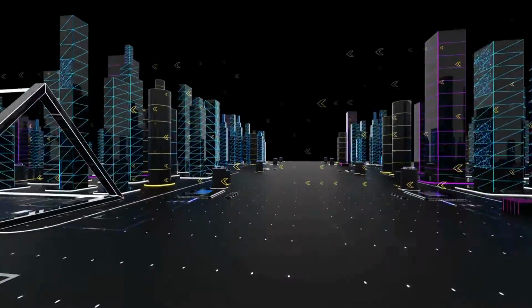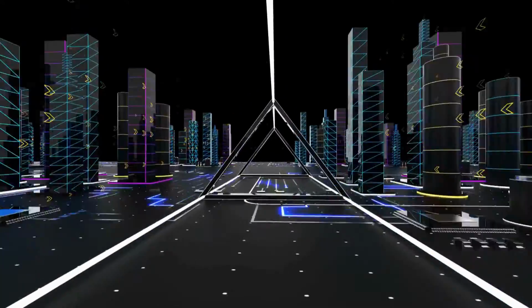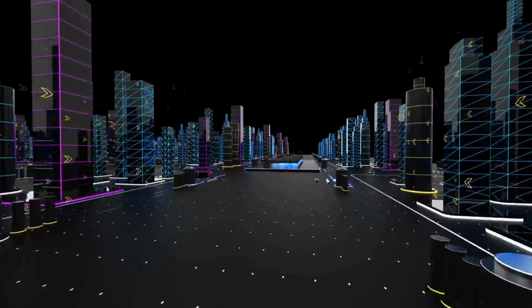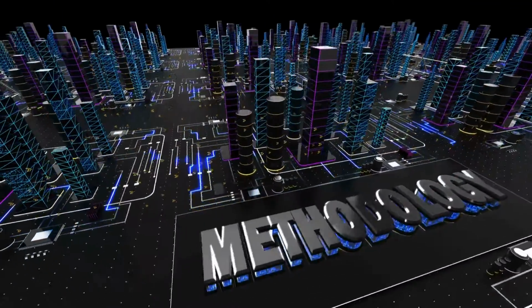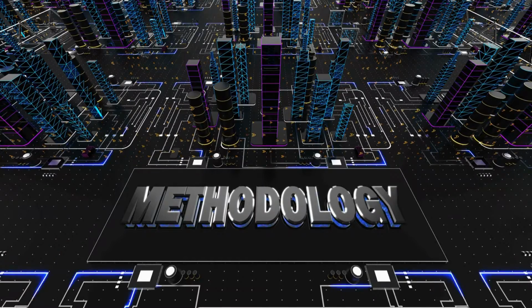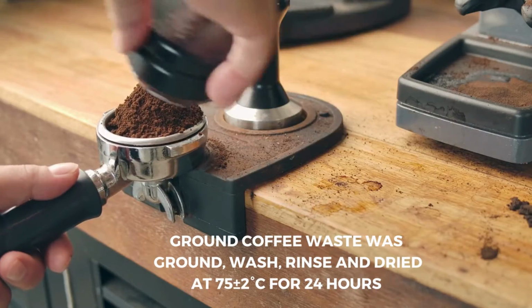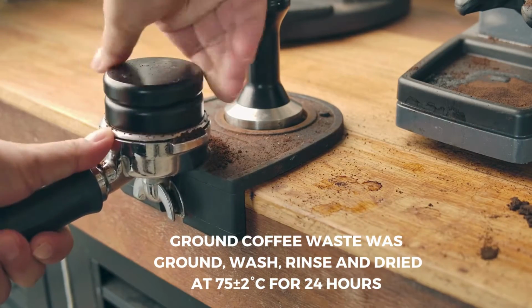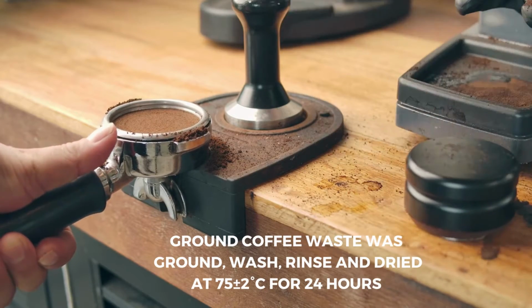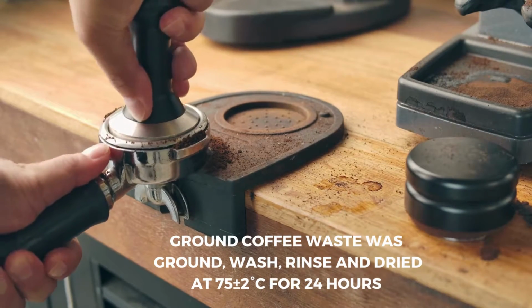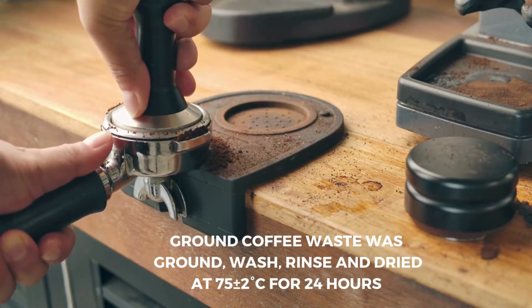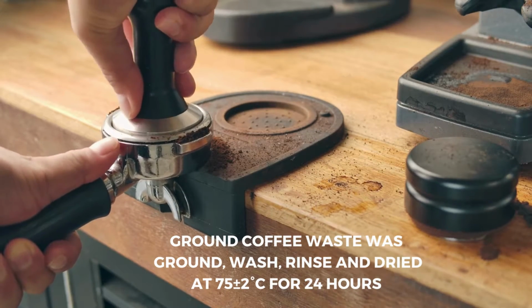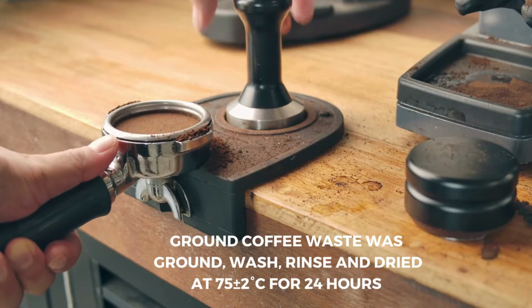Are you wondering how the product has been made? So now, we will move to the most interesting section of the research, which is methodology. In order to synthesize treated activated carbon derived from ground coffee waste, firstly the ground coffee waste was ground, then washed, rinsed, and dried at 75 ± 2 degrees Celsius for 24 hours.